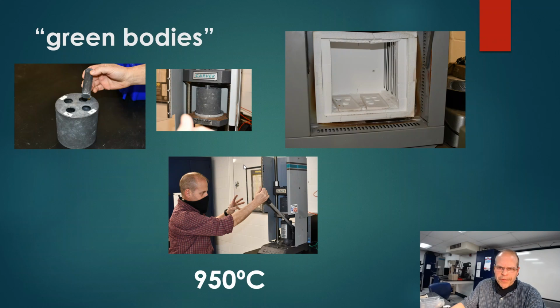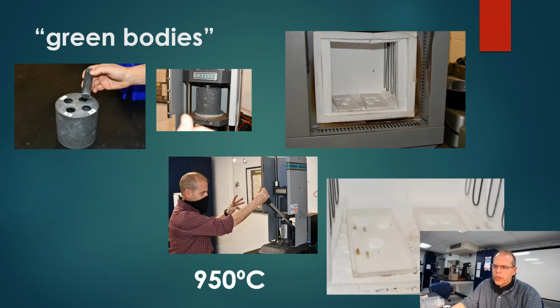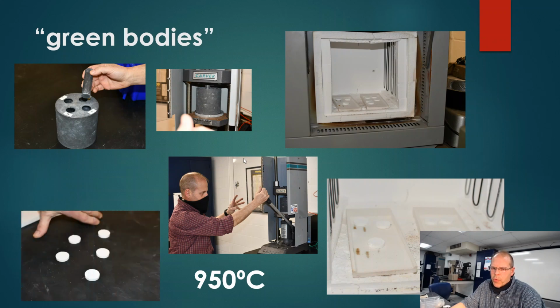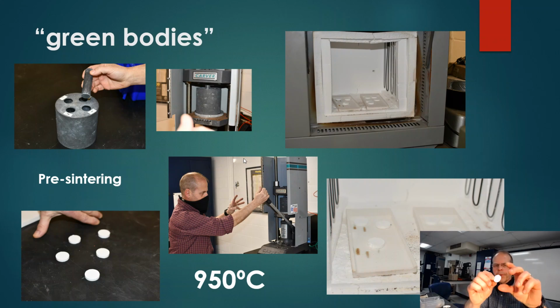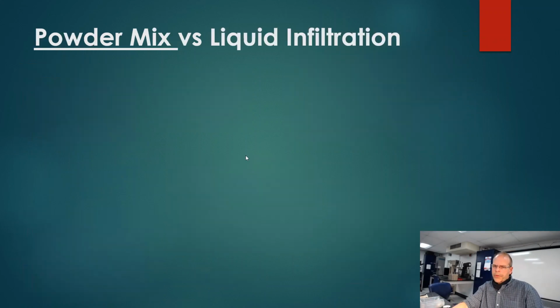As you would imagine, these are pretty fragile when they come out. It's basically small particles of aluminum oxide just pressed together. So we pre-sinter it, and by pre-sintering, we actually heat these things to 950 C for about 4 hours. What you end up with is a little puck, which is a lot easier to handle. So again, we've turned the powder into this little tiny disc right here as we go along. We're going to make this stuff, ZTA, two different ways. The first way is we're going to do a powder mix.